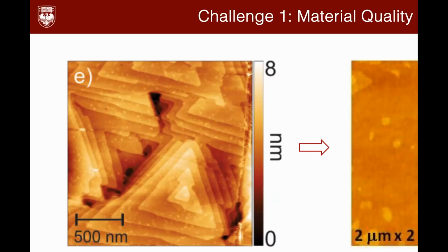In order to really show the quantum effect, such as the quantum anomalous Hall effect, we need to go from good quality film to supreme quality film. That's what's shown on the right. This one I just took from this famous paper by Professor Qikun Xue's group back when he was still at Tsinghua University, on a chromium-doped bismuth antimony telluride. You can see there's a qualitative difference between these two. For the film on the right, you need a really, really flat film that has uniform thickness across at least a micrometer range. So how do we go from the left to right? And if we can overcome this challenge, what kind of exciting physics can we realize?